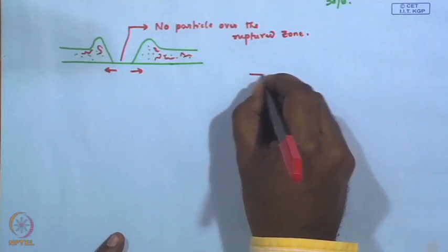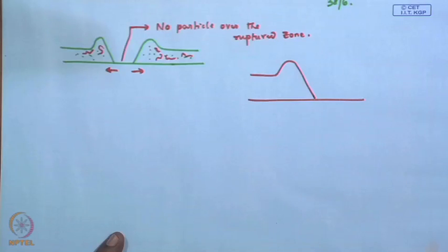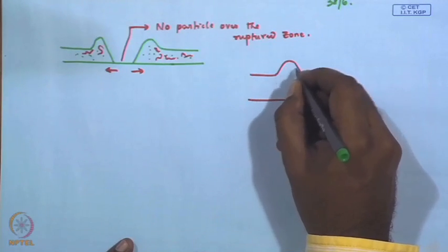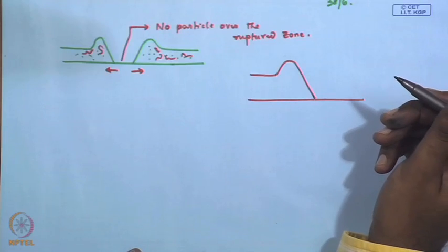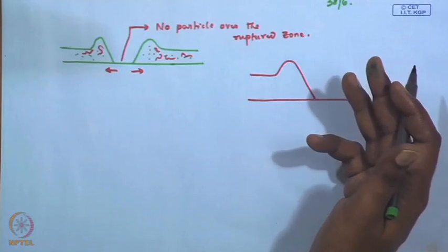So, this allowed these gold nanoparticles to sort of migrate, we are just showing one side of the rim, at a faster rate as compared to the long chain polymer molecules, which also diffuse, as you know that the rim formation itself occurs because there is a mismatch at the rates at which the polymer is dislodged from the surface and gets redistributed to other intact parts of the film.